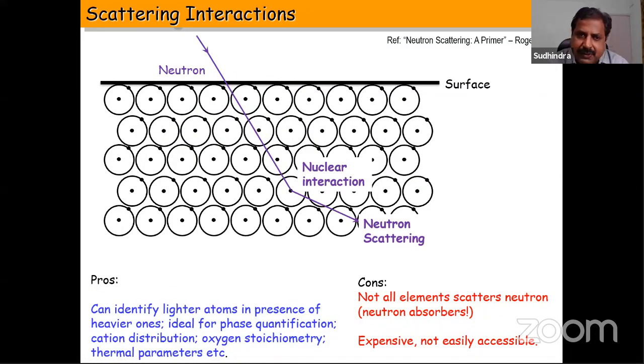Now comes neutron diffraction. The neutrons can interact with the nucleus of your material and get scattered because of this nuclear interaction. The advantage here is that it can identify lighter elements in the presence of heavier ones, because the nuclear scattering doesn't depend upon the atomic number, but on the nuclear energy levels. If you're working with, say, ionic solids, where you have to identify the cationic distribution, it's very convenient to do that with neutron diffraction. It also helps in identifying the oxygen stoichiometry, because oxygen, being one of the anions, can be easily identified. You can also identify the thermal parameters, and you can also do phase quantification.